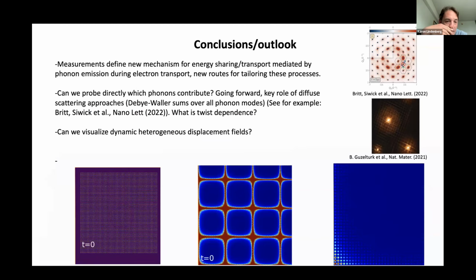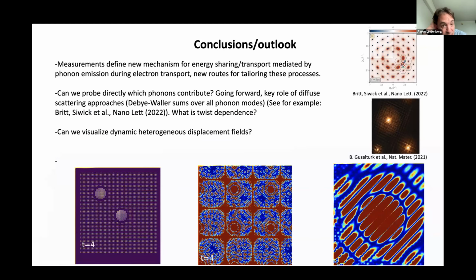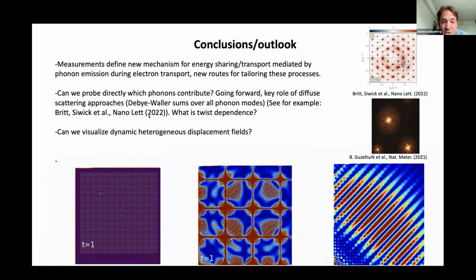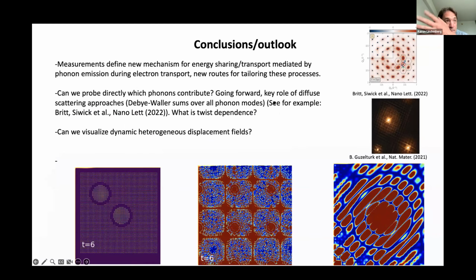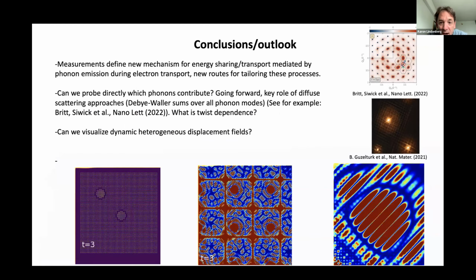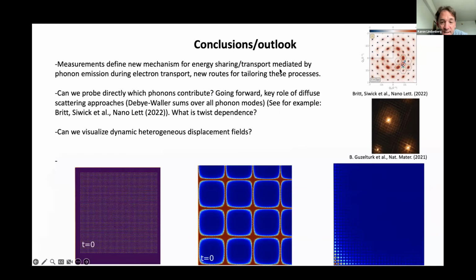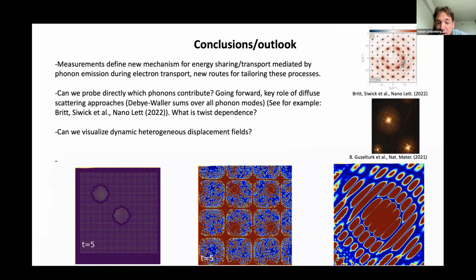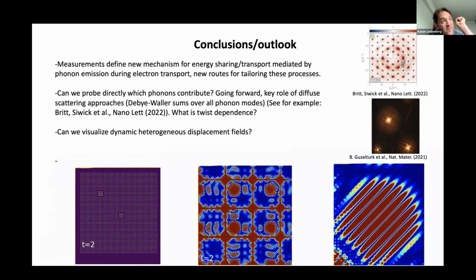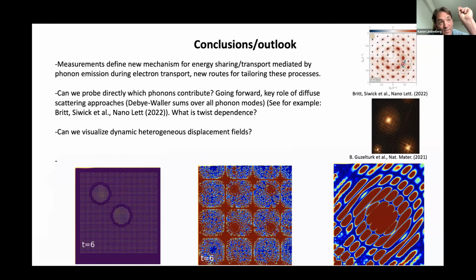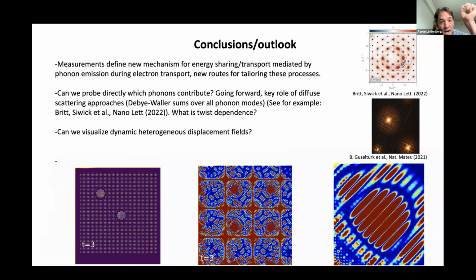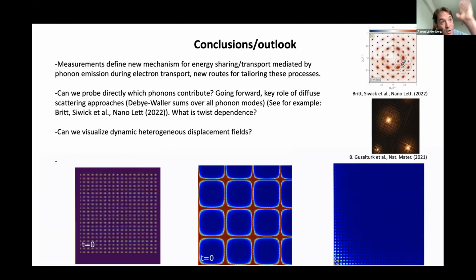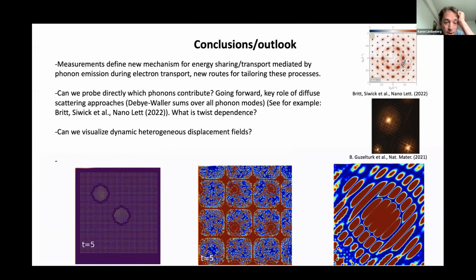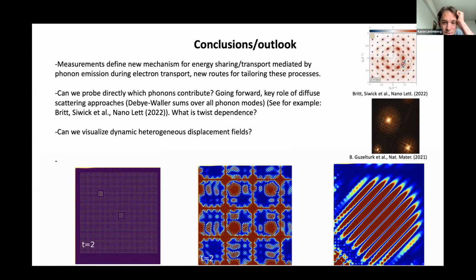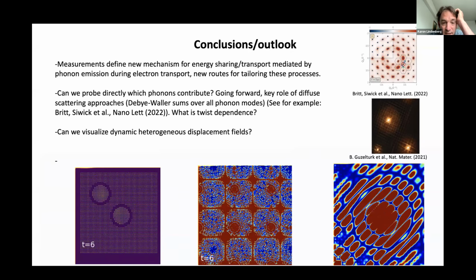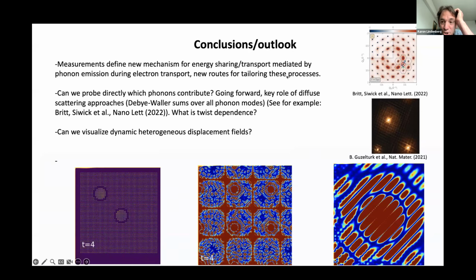And so a key direction going forward is to extend these approaches to go beyond just measuring the intensities of Bragg peaks and really try to probe the diffuse scattering itself. In a diffuse scattering measurement where you probe off of a Bragg peak, you have momentum specificity, and you can define a particular momentum transfer and directly probe the response of, say, a phonon associated with that particular momentum. So these are key ways in which one needs to push going forward.